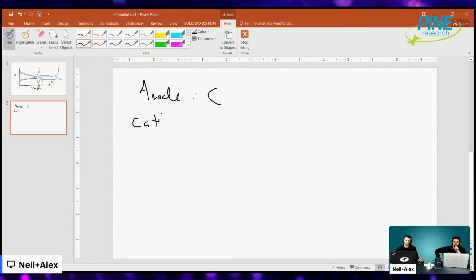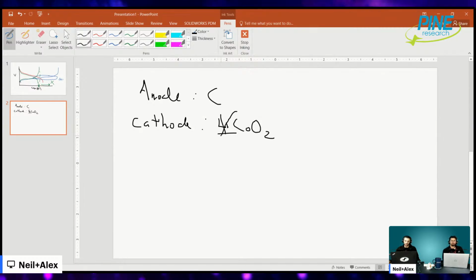The cathode is usually a transition metal oxide. So let's just use the simplest example, one of the first ones, lithium cobalt oxide. Okay. You can see here, if you have these two materials, the only place lithium exists is in the cathode. Initially, it's lithiated. So if you don't have lithium cobalt oxide, and you just have cobalt oxide and carbon, well, there's no lithium. You don't really have a battery. So usually the cathodes are pre-lithiated. Okay. That means it's fully discharged. Lithiating the cathode is discharging it.